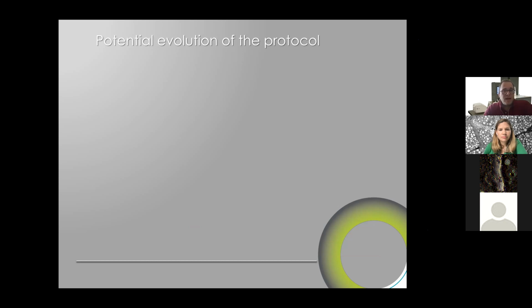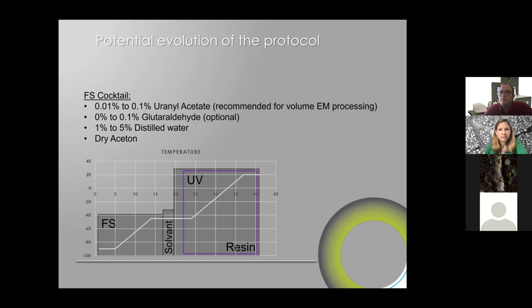And so the last thing, because it has been asked several times, and I think is important, is how the protocol we've been recommending so far is subject to evolution and what could be improved or not. So what we've seen is that the freeze-sub cocktail from 0.01% starts to be functional, up to 0.1%. The glutaraldehyde, as I mentioned before, gives some higher contrast. What is the mechanism behind? I don't know exactly, because it's definitely not a contrasting agent. Keeping water in the freeze-sub cocktail is essential, and with dry acetone we have to be strict on the volume of water we have in.